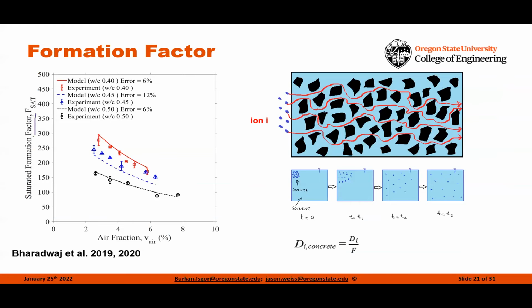So we could take this entire model and we could predict things like the electrical resistivity or the formation factor. So here what we've done is we've shown the formation factor versus the air content of a mixture. And what we see is when the system is completely saturated, the formation factor or the electrical resistivity is dependent upon the air content, but we're able to use this model to predict the experimental results in these particular cases very, very well and capture these factors. If we don't vacuum saturate the system and we only saturate the pores, what we notice is these lines become flat lines that are independent of the air content in the system.